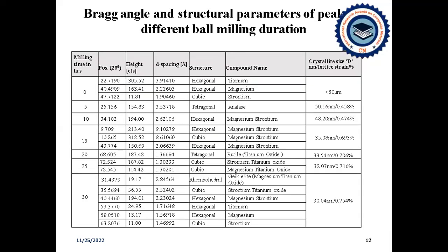These are the Bragg angle and structural parameters of the XRD peaks at different ball milling durations. We can observe that at the end of 30 hours of ball milling process, binary phases are formed. That means the binary phases of strontium titanium, magnesium strontium, titanium oxide, along with the elemental phases titanium, magnesium, strontium, were observed at the end of 30 hours of ball milling process. It represents that the alloying has taken place between the titanium, magnesium, magnesium strontium, and strontium titanium.